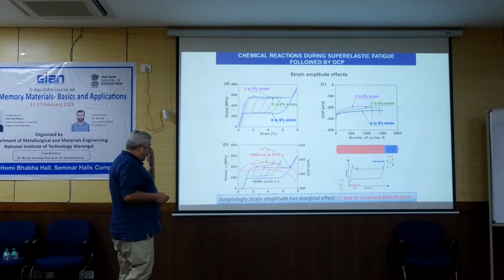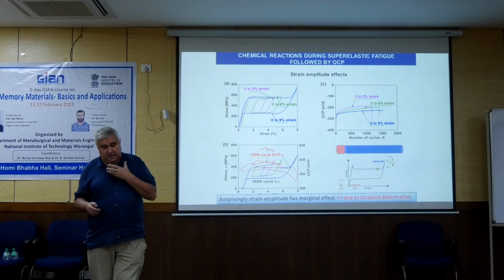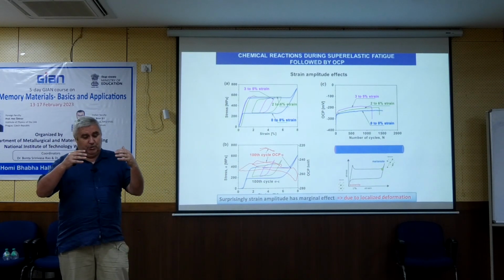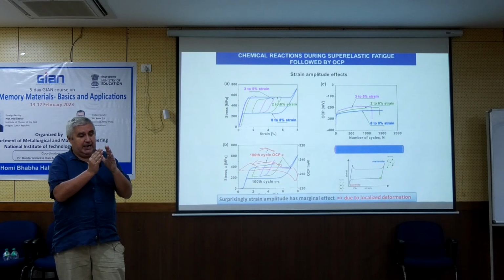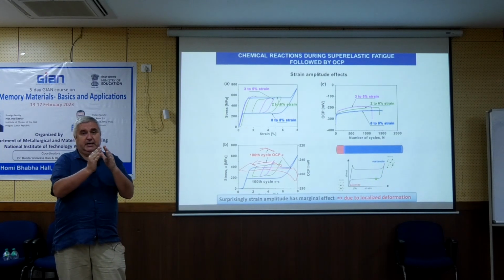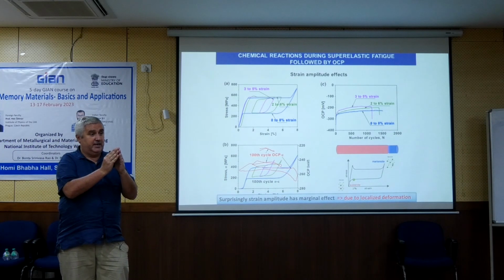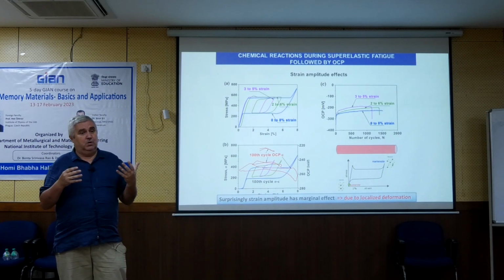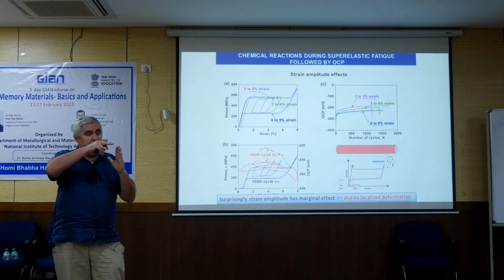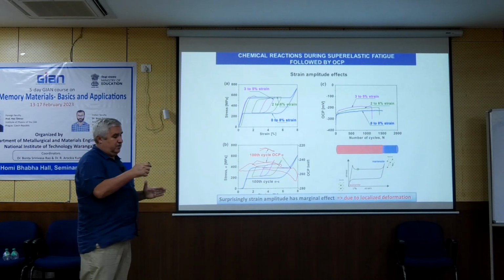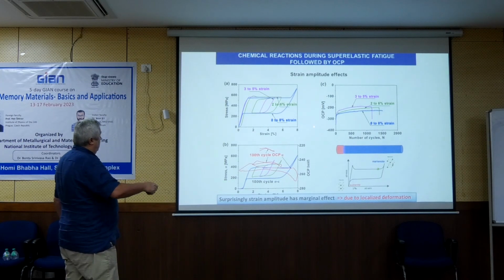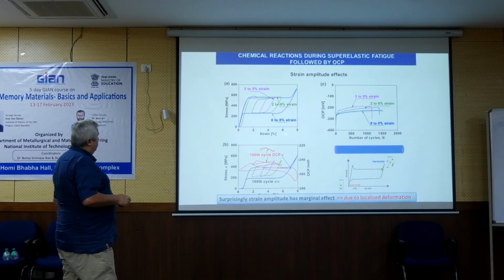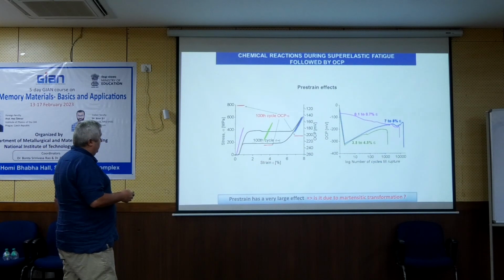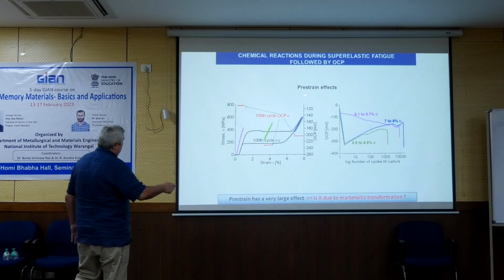This is the main problem: if you have a stent, the deformation on the surface is not homogeneous. You have some parts which deform superelastically 5%, and some parts which remain elastic. So we wanted to know, what if we cycle only elastically the austenite, or in the middle? We did such measurements for strain amplitude and pre-strain. Pre-strain is more interesting.